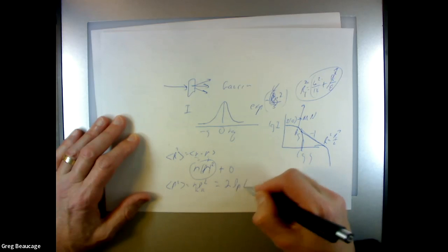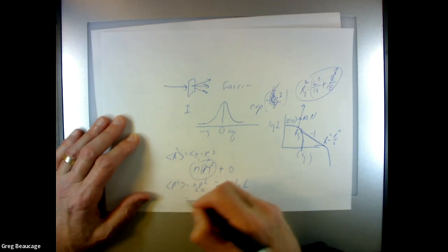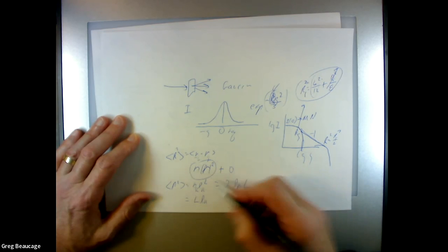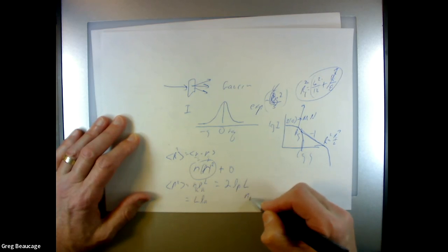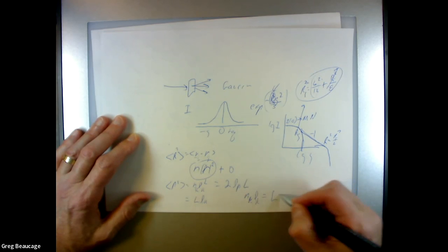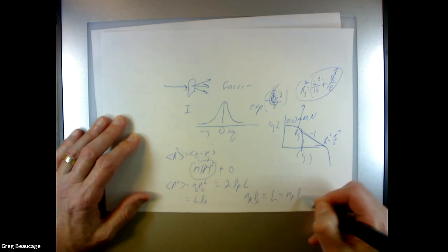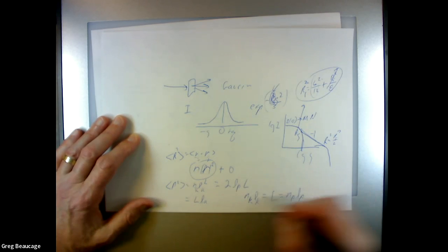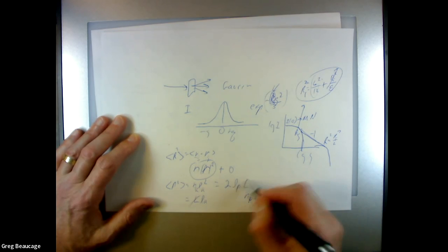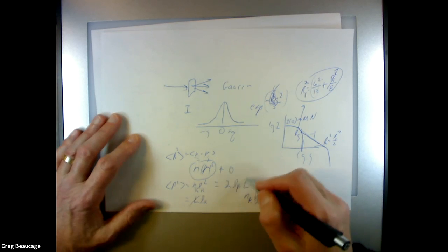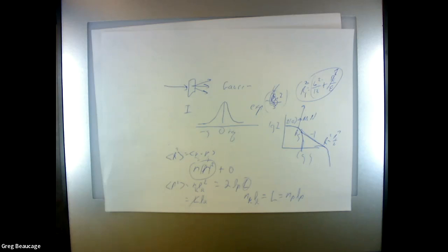That this thing is going to be 2LP times L. This thing equals L times LK, because NLK is the same contour length. So NK LK equals capital L equals NPLP. It's the same chain, stretched out the same. So those terms drop out, and then you just have LK is 2LP. But that means you have to have a big chain for that to work, an infinite chain.